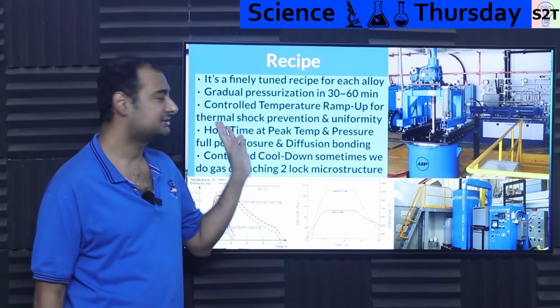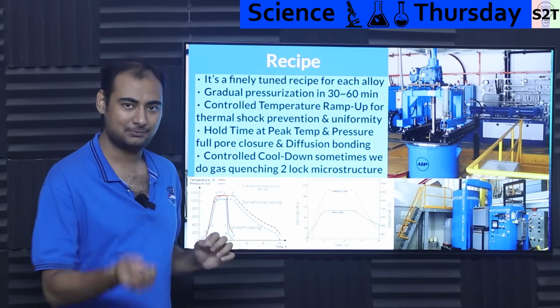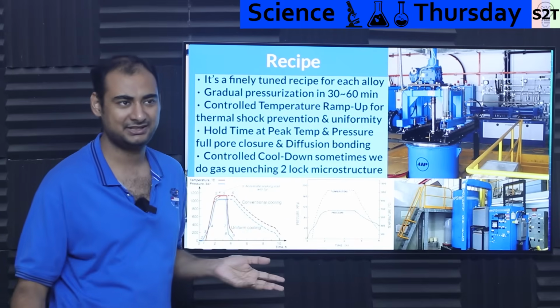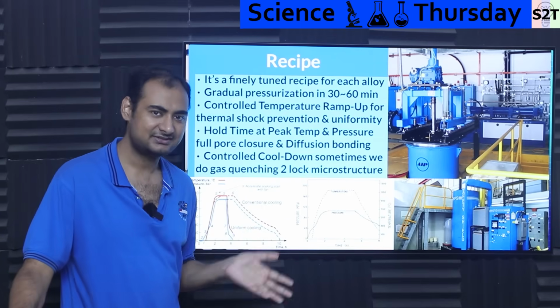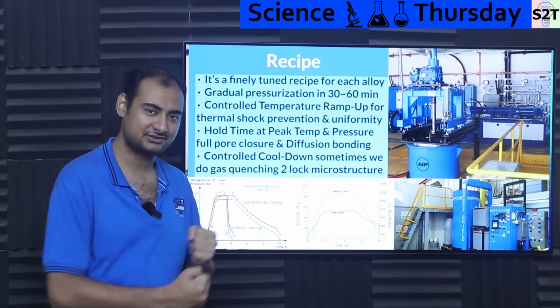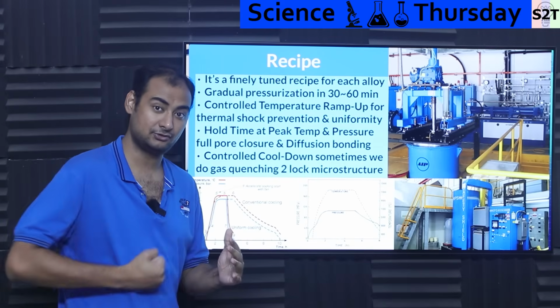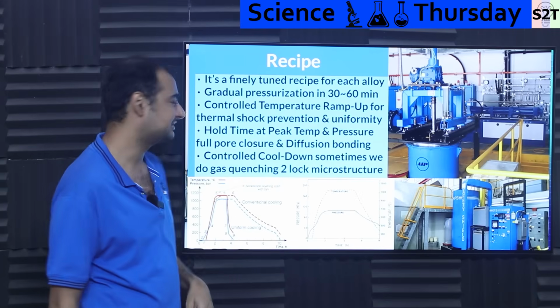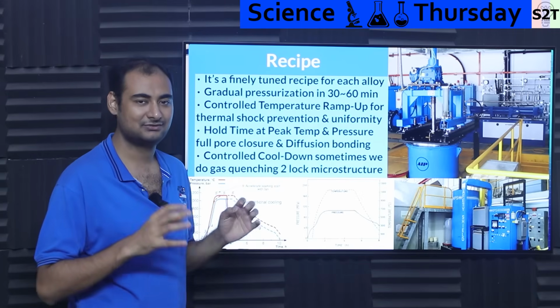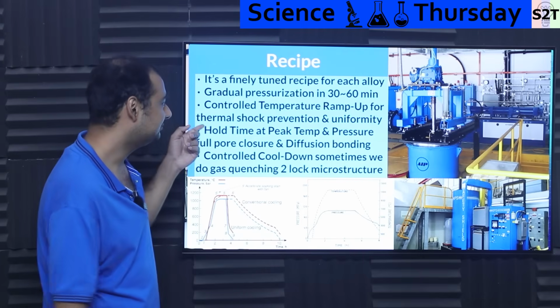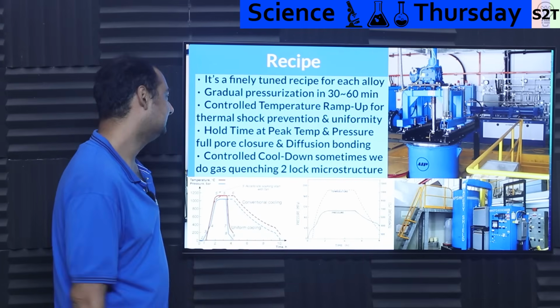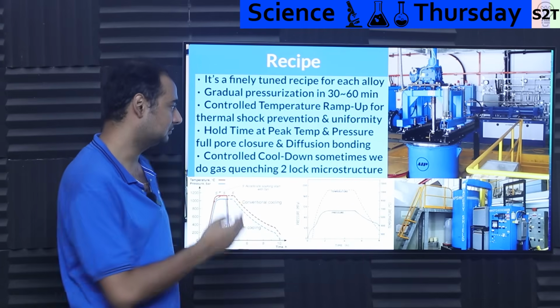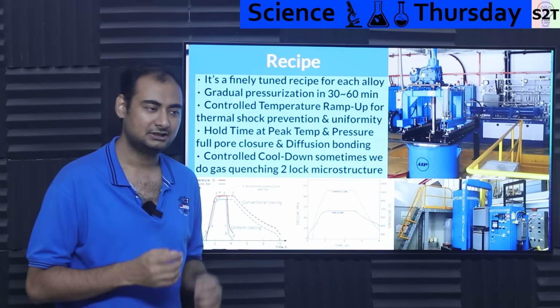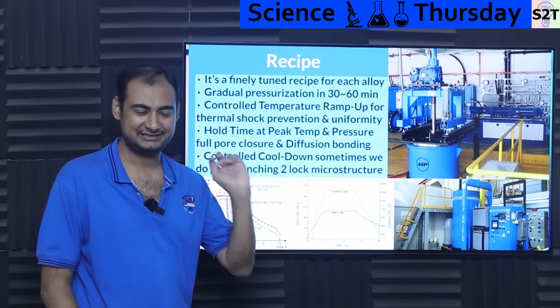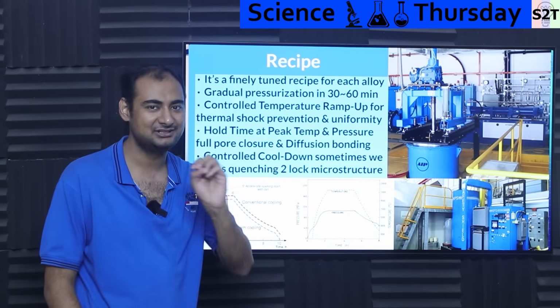So generally we start to gradually increase the pressure. You open the argon bottle that is barely 100 to 150 bars, and then you flush it, and then the compressor starts, like, let me apply some hydraulic oomph to it. And then you slowly ramp it up over around 30 to 60 minutes. You take your time, because you do not want to shock the system. And then you control the temperature ramp up. This ramp up has to be done this way so it does not give thermal shock. No matter how strong the alloy is, if you give it bad enough thermal shock, it will shatter like glass.